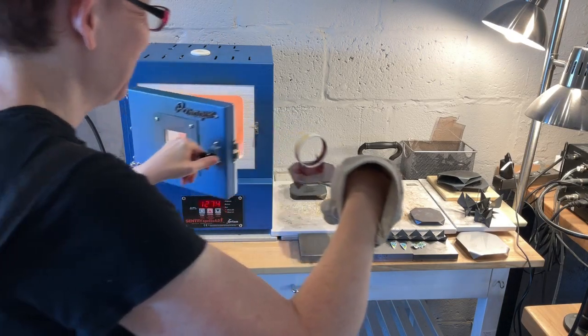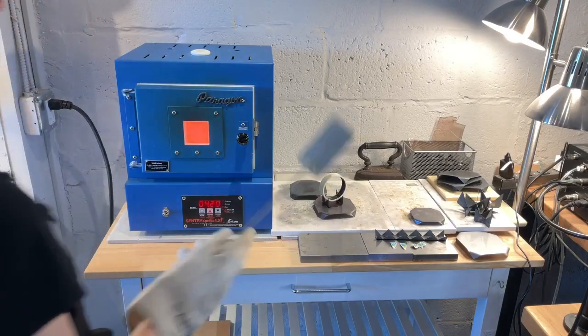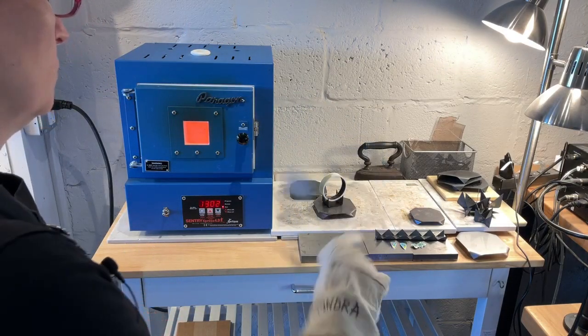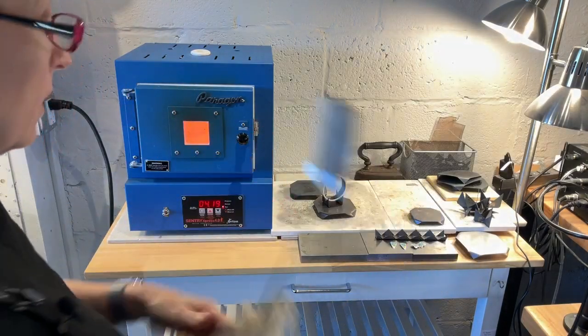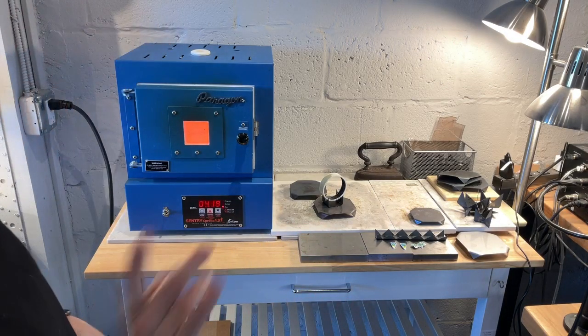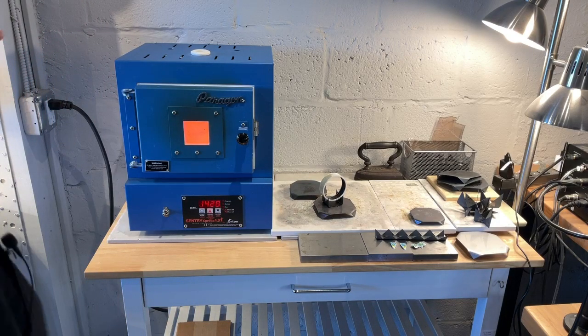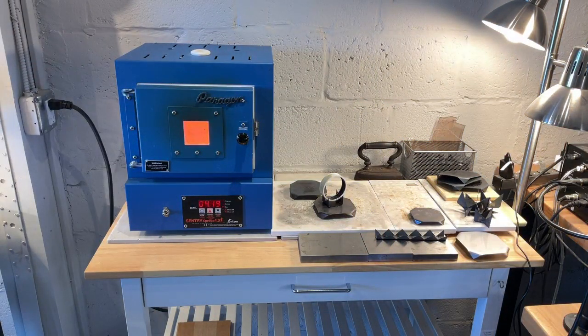Oh, I know. It's fine. I did not let it dry long enough, and I can see I got some browning. Good, but it doesn't matter because we're going to be artistically placing foil over there. So I didn't really care, but if you're ever getting results like this, and we'll look at it when it's cool, this is one of the things that causes your flux to turn brown: not sufficient time to cool and dry. So we'll let that cool.